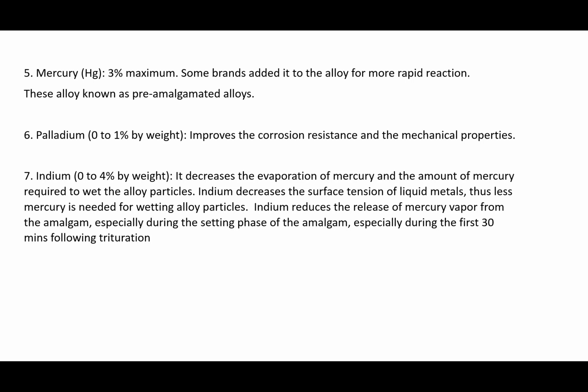Then we spoke about zinc: it is for better handling properties, reduces brittleness, works as a scavenger for the available oxygen, but zinc has a disadvantage when the alloy containing zinc is contaminated with moisture, which can lead to delayed or secondary expansion. Palladium improves mechanical properties, and indium reduces release of mercury vapor from the amalgam.